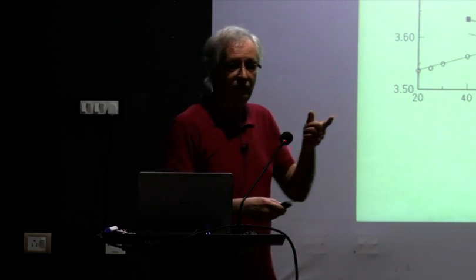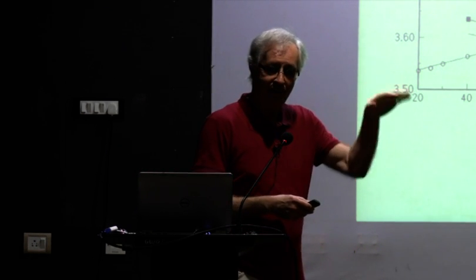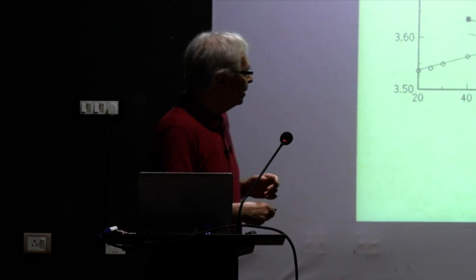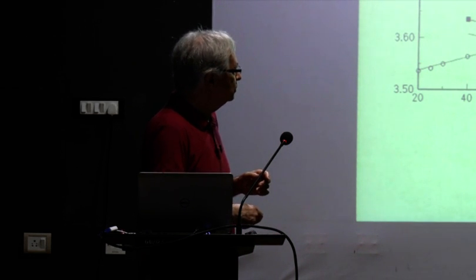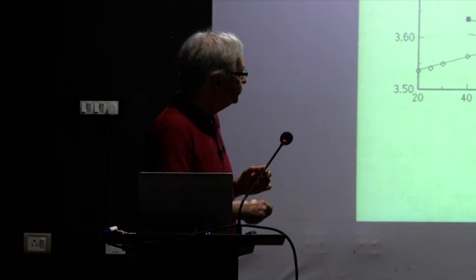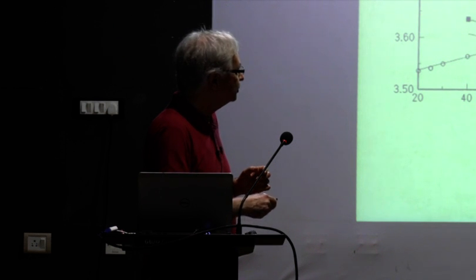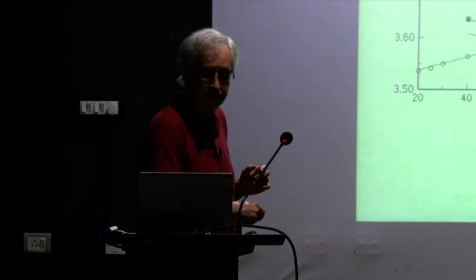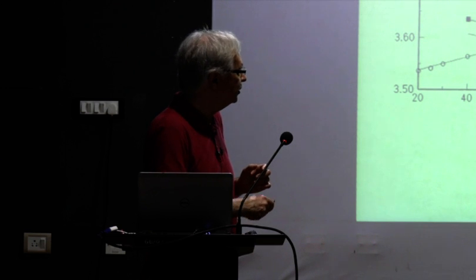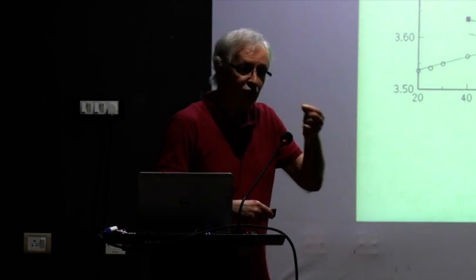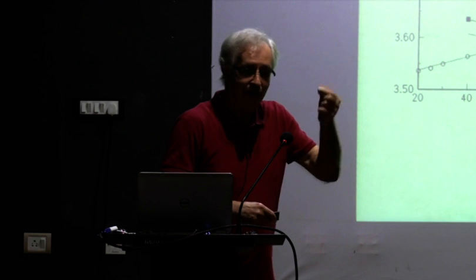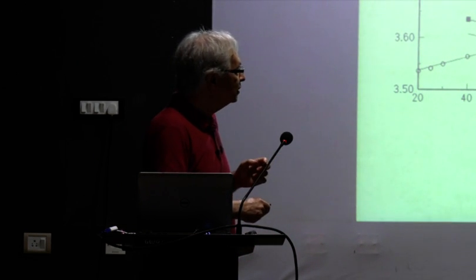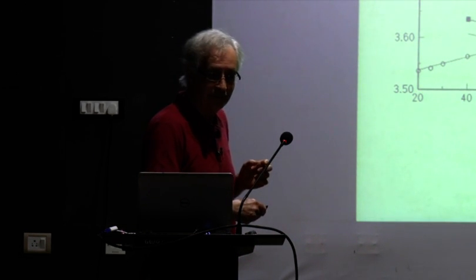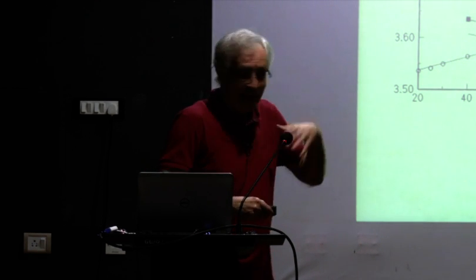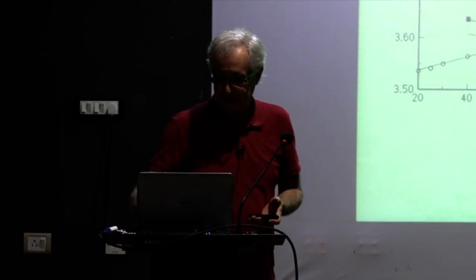Another point that tells you why you should have a maximum is that if you calculate the average thermal expansion coefficient of this whole thing from here to here, that turns out to be larger than the thermal expansion coefficient that you have here. So this thing has to go through a maximum somewhere.